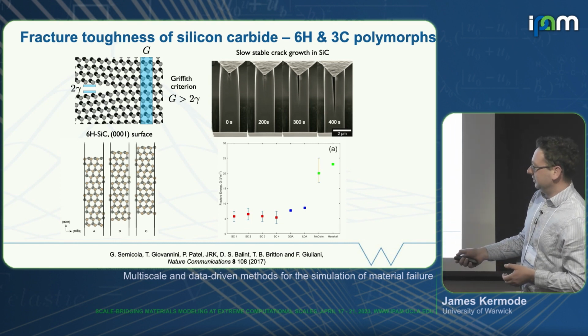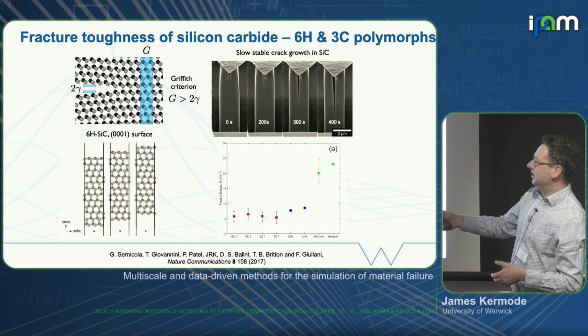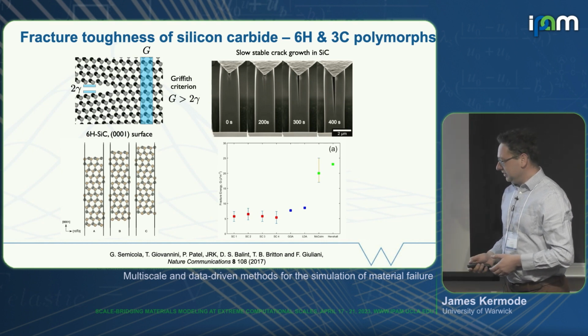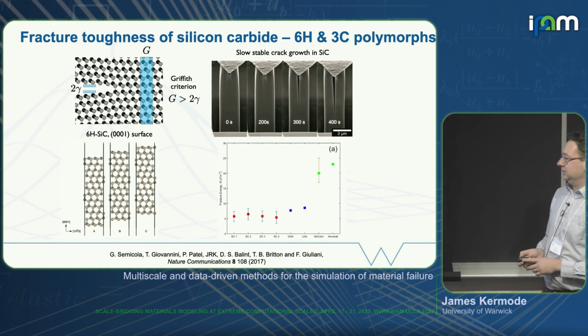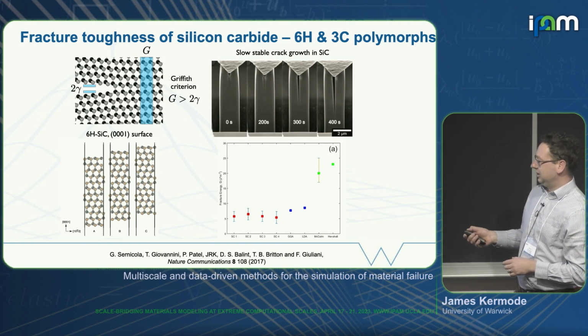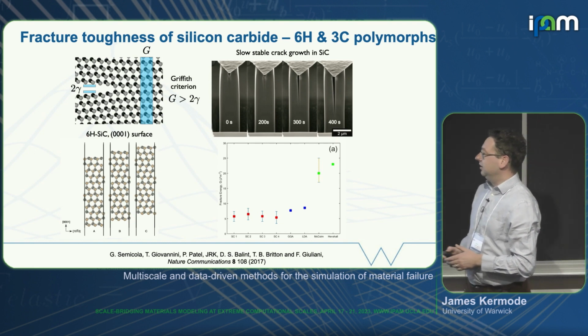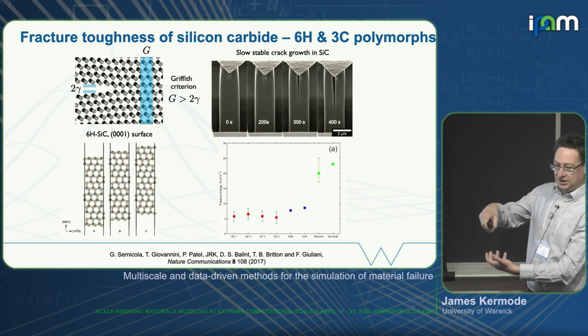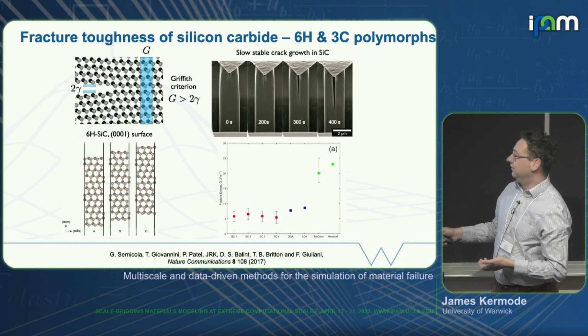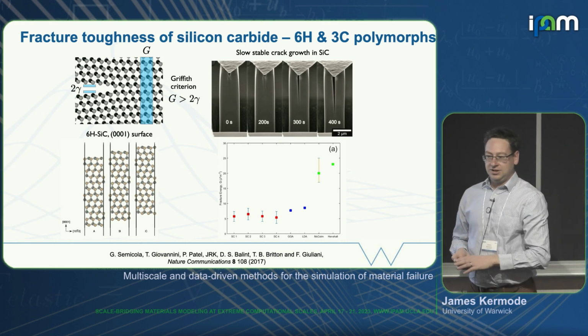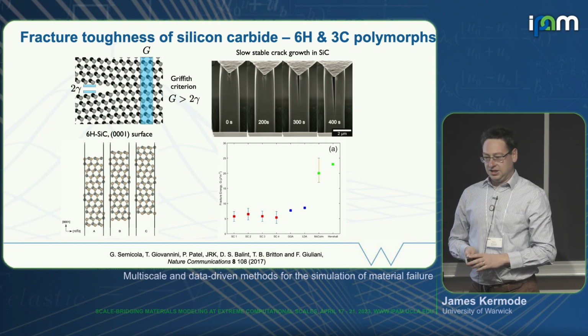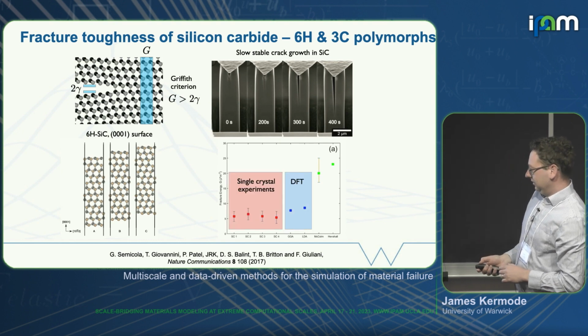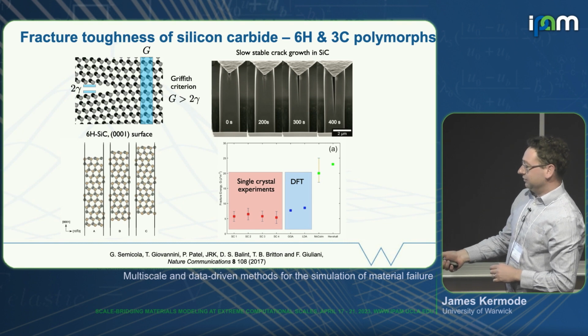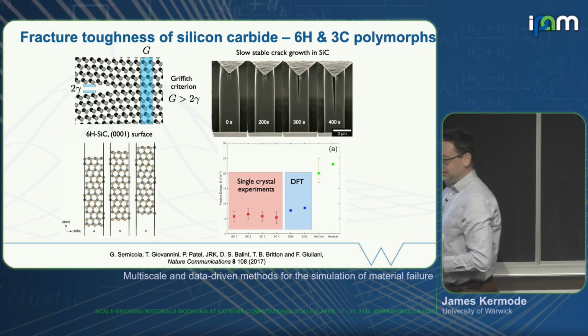So you can do a few of these calculations, you can calculate surface energies, and thereby make a prediction that's reasonably accurate for the fracture toughness and that compares well with experiments. These were experiments done by Finn Giuliani at Imperial, double cantilever slow crack growth. So the crack grows over hundreds of seconds, it's kept stable, and therefore you can accurately determine the fracture energy, and it's in pretty good agreement with what we calculate, directly estimated from the surface energy.